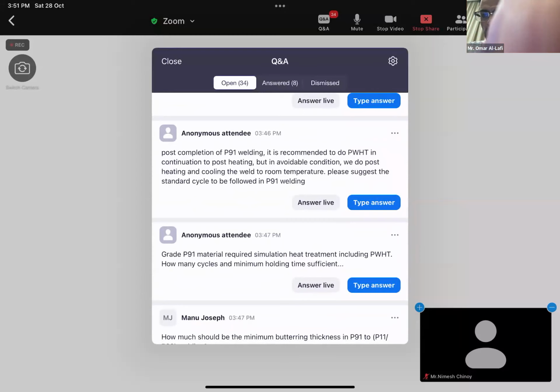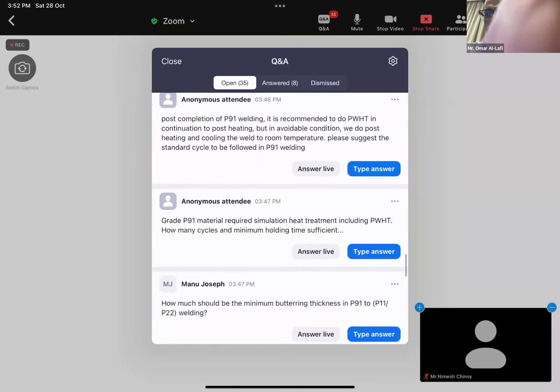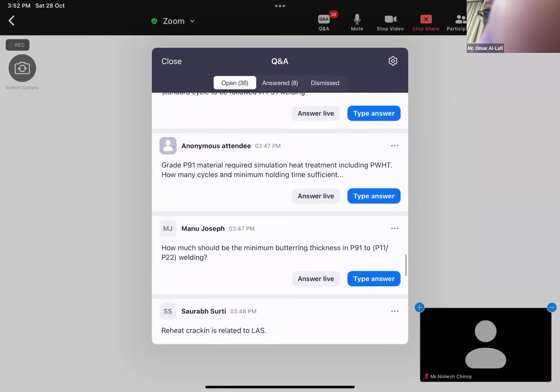Suggest the standard cycle to be followed. The standard cycle for cooling is to cool it in still air to room temperature or to below 100 degrees Celsius. So we remove the heating pads, the insulation, we remove everything, we let it cool in still air. Does grade P91 material require simulation heat treatment, including PWHT? Yes. Simulation heat treatment is a good practice to be done. And also if you can have this simulated in the WPS qualification itself, that's fine. So you can have a simulated heat treatment during the WPS qualification.